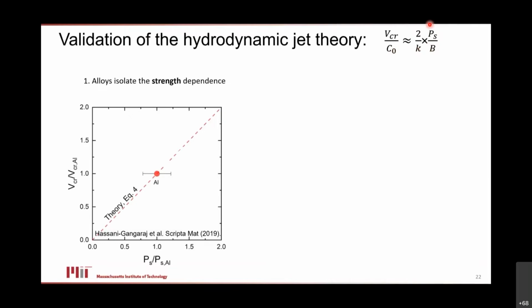The way we approached that was to take those data I showed you for aluminum, and now if we keep the base metal as aluminum, but we do some light alloying and heat treatment, you can actually go to aluminum alloys, and in an elastic sense, they're basically the same. They have the same speed of sound and the same modulus to first order, but their strength is different. We can strengthen aluminum by 50%, and exactly in line with this scaling law, we measure that their critical velocity goes up in proportion. So that linear scaling between strength or spall strength and the critical velocity is validated with those kind of experiments.